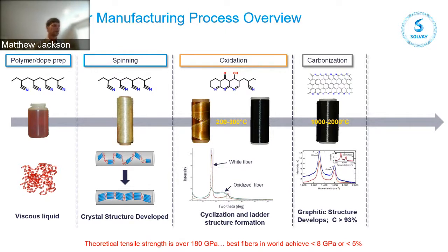And so the theoretical tensile strength is over 180 gigapascals. That's if you take just graphite or graphene. But at the end of the day, we don't realize properties even close to that even today. The best carbon fibers in the world are around 8 gigapascals in strength, or only 5% of the total performance. And so there's still a lot of room that we can grow, and there's still some improvements that can be made in the carbon fiber structure itself.